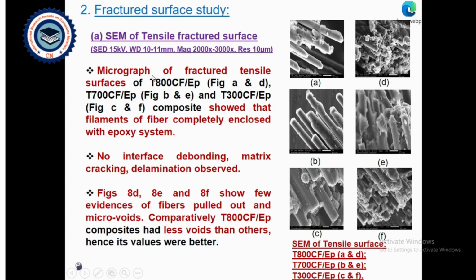Fractured surface study. The SEM of tensile fractured surfaces shows T800 composites in figures A and D, T700 epoxy composite in figures B and E, and T300 composite in C and F. They showed that filaments of fiber are completely enclosed with the epoxy matrix system. No interface debonding, matrix delamination, cracking, etc.